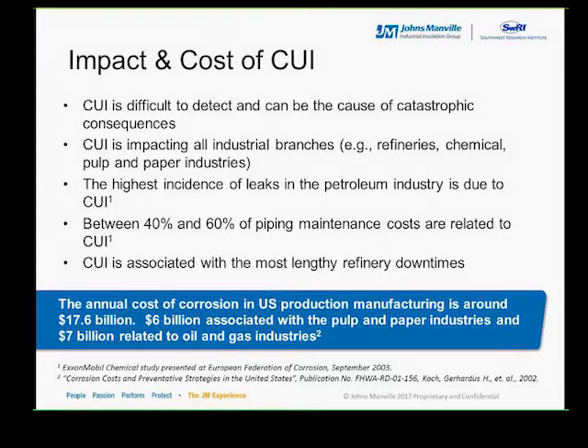According to a study presented to the European Federation of Corrosion, the following conclusions were extracted from that investigation. The highest incidence of leaks in refining and chemical industries are due to CUI and not to process corrosion. Over 80% of most piping leaks occurs in diameter less than 4 inches. Between 40 and 60% of piping maintenance costs are related to CUI, according to another study back in 1992. And last, CUI is associated with the most lengthy refinery downtimes.